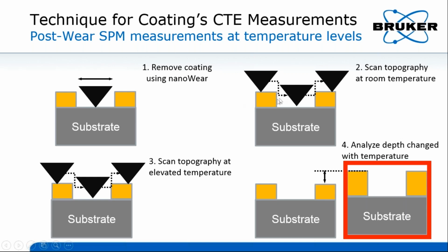After that, we collect the image of the nano wear, including the worn region and the original region. And the third step is to repeat the in situ SPM at different temperature levels. Finally, the depth change of the worn region, or the height difference between the worn and the original regions, is related to the temperature change. And then we can analyze the depth change with the temperature change to determine the CTE using the linear CTE definition.